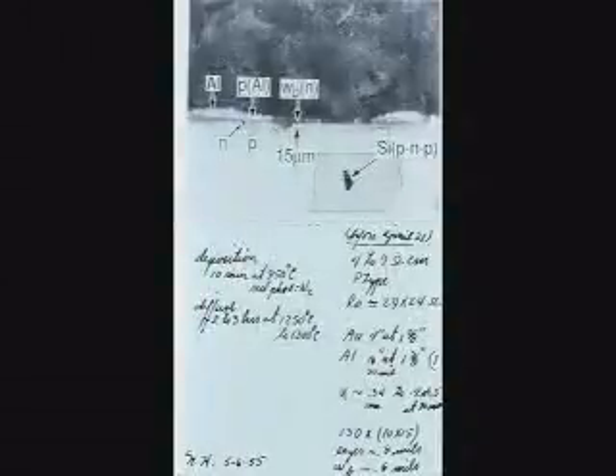And we got there. Now, this is not going to be very good, but it shows you, I had squirreled away a piece of the crystal, which was the silicon PNP, and there was a cross-section on this Polaroid of that P-type crystal here, an N-type diffuse region, and then regrown from aluminum P region here, so it's a PNP. And then I had some of my notes on the back side, which I moved to the front side. I cut it and moved it so that the photographer could show what I had written on the back and what we had done in diffusion and so forth. Let's not worry about that. But the date on it is, that's my initials, that's 1955, and spring of 1955.